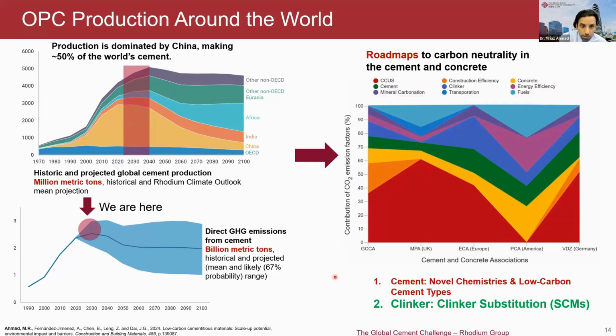Other approaches are novel chemistries and low carbon cements, like we try to find alternative cementitious materials, not OPC. Another approach is reducing the clinker factor. Normally, if we talk about supplementary cementitious materials, we use around 10, 20, 30%, except slags. Of course, slag can be used in a higher percentage. Besides slag, for all of the other materials, the percentage is limited to 10, 20, or maximum 30%. So in today's webinar, I will be discussing this roadmap, like how we can reduce the clinker at a higher level. We call this kind of cement ultra low clinker cement.